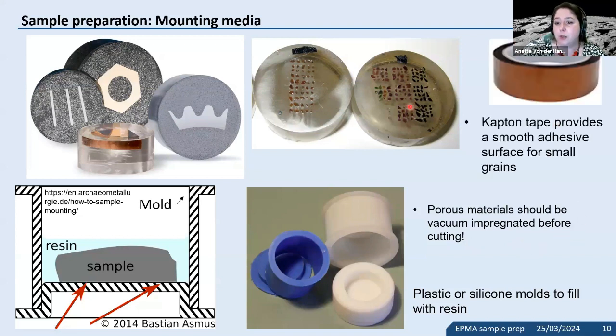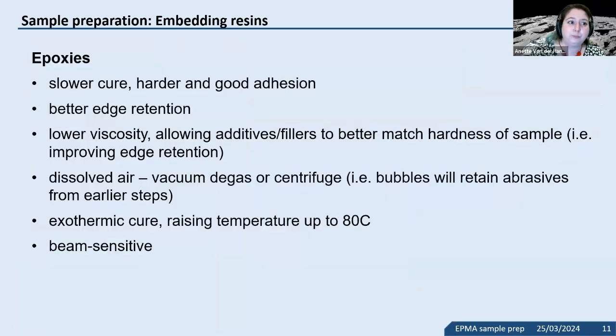My personal tip, specifically if you do grain mounts: people use all kinds of adhesive, including just normal packing tape. But if you have very, very small grains and you want to start out with minimal polish, I'm a big fan of Kapton tape, that's the brand name. That usually provides a very smooth surface for small grains. So I then usually just have to start polishing at 9 microns, because I don't have to take much roughness away, and that helps me preserve these small grains.